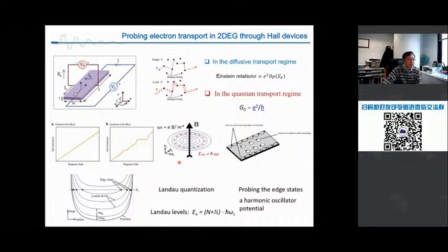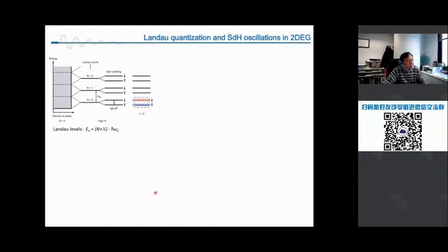And we need to measure these Landau levels through edge states, because the bulk inside 2D materials is insulating, and is probed by transport. So at the edge, you have a band edge crossing the Landau level, and in that region you detect this Landau level transport. This is the Fermi energy surface, and this occupies states. Once you apply a magnetic field, Landau levels form, and in each Landau level there are two states: spin up, spin down, spin up, spin down, and so on.